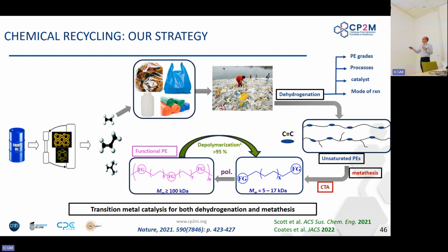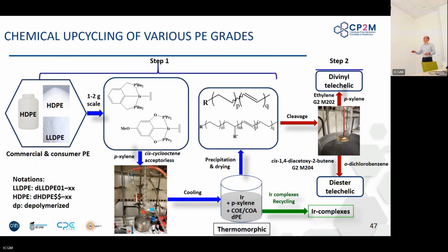If you introduce unsaturation on a polyethylene backbone, after that, you should be able to do metathesis and to chop them down to something smaller. And this is what we do, and we do that with several catalysts. We do that with iridium. So iridium is costly, but you can lower the amount that you use because these are very robust catalysts. You just need to be able to heat the system to 150, 200 degrees, and you are able to introduce double bonds. And after that, by metathesis, you can cut precisely the polymer.